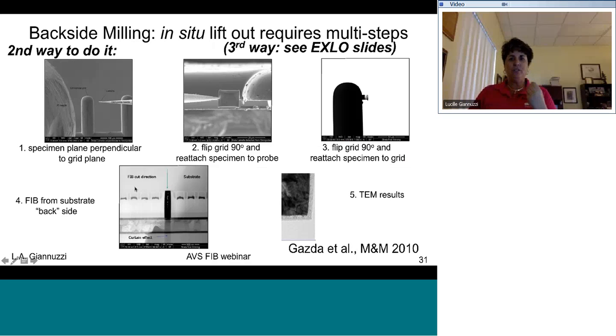Okay, another way to do this requires multiple steps inside of your FIB-SEM, and this requires multiple releases and tilting of the grid. So here's the lift out. The grid is perpendicular to the sample. Then you can flip the grid, grab it again, flip it over, and then you can eventually get the sample upside down relative to the grid by cut, release, cut, release, cut, release.